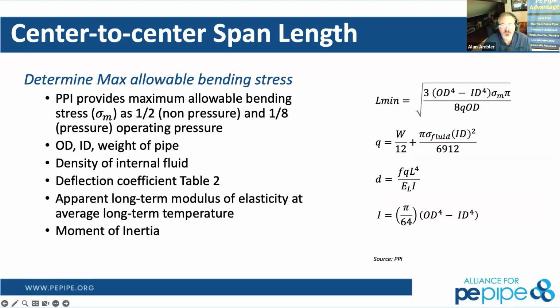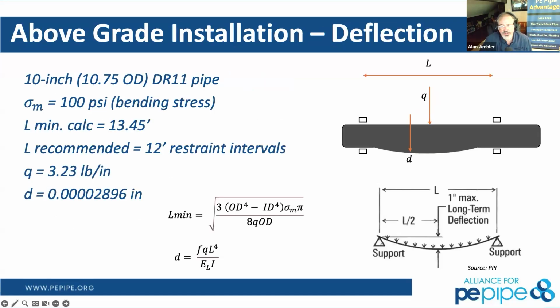So here's just the equation that we have. We do translate this into the calculator for you as well. While we are looking at span-to-span length and the stresses determined within it, we are also looking at the fluid density and weight as it's conveyed through this pipe. So we have the pipe, plus the weight of the fluid within the pipe, and then we will translate that directly into the deflection calculation as we're seeing here. So for a 10-inch pipe, when we're looking at 100 psi bending stress with 13.45 feet in between spacings, we're looking at 0.00002896 inches of deflection. So we are not deflecting a whole lot within this pipe, and it's simply not moving for us in that process.